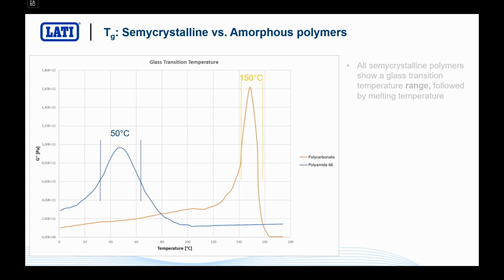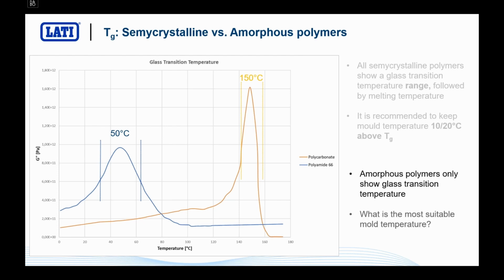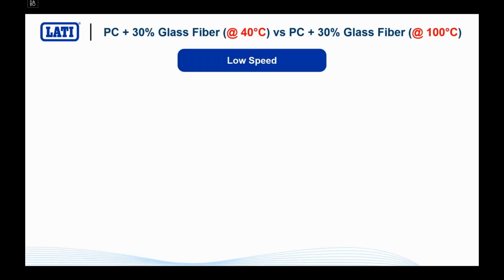What happens with amorphous plastics? Amorphous plastics have a much narrower glass transition temperature, and we want to stay as close as possible to this temperature. Actually, for semi-crystalline it is recommended to stay 10 to 20 degrees C above, while for amorphous it is recommended to stay more or less close to the glass transition temperature, for the reason that we are going to find out right now. The point is that polycarbonate is not normally molded at 150, it's molded at 100 something. Let's see it with our design of experiment.